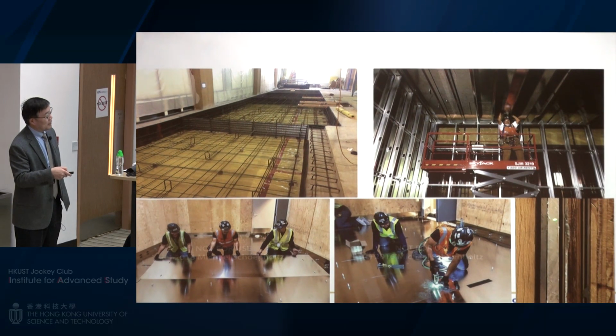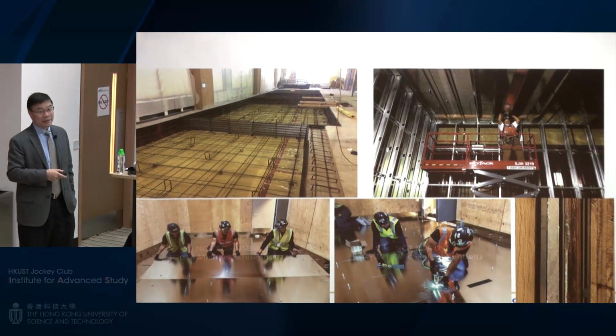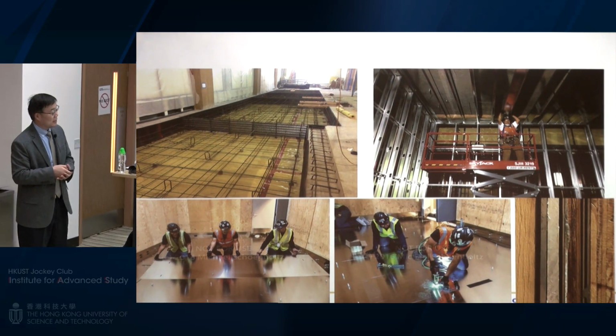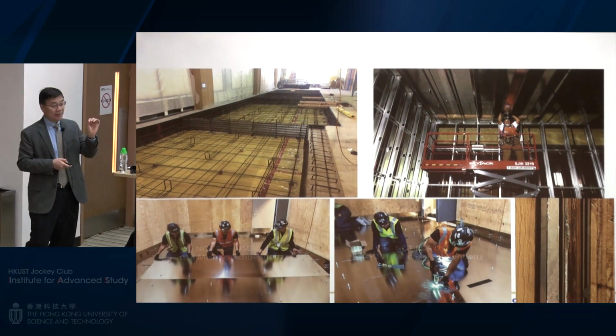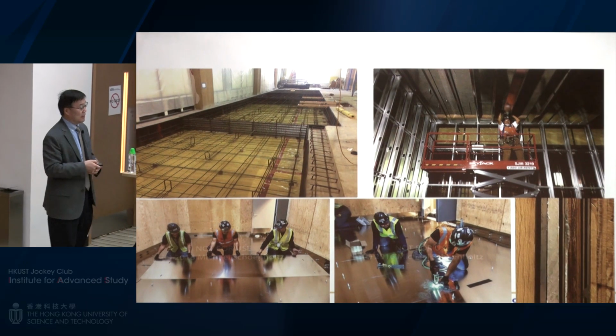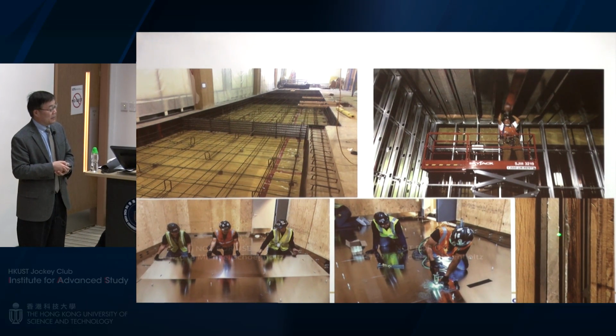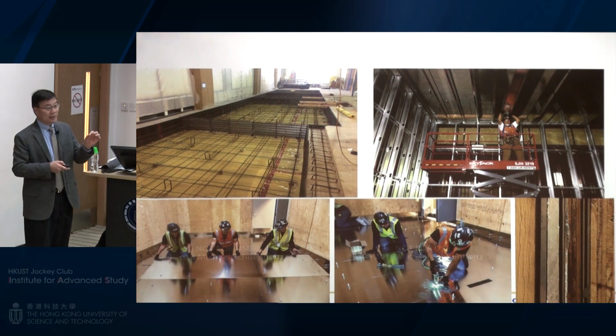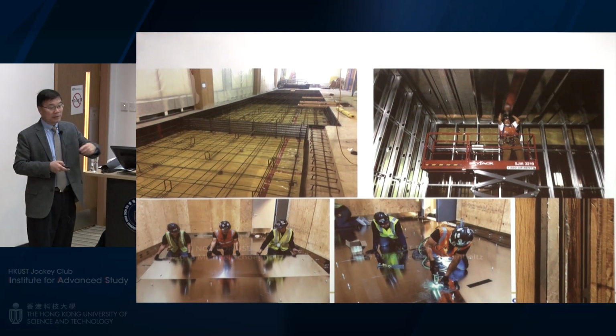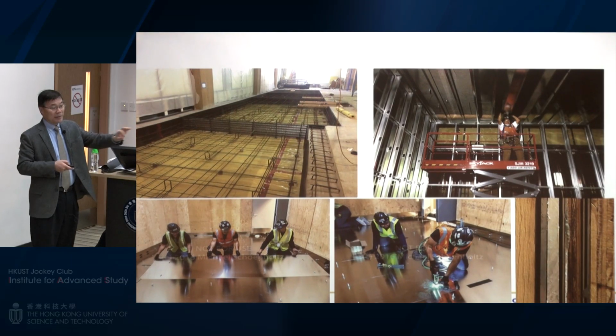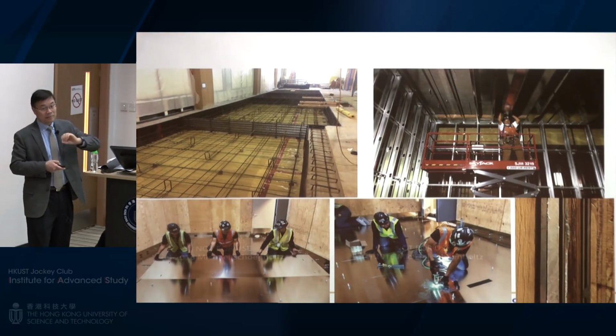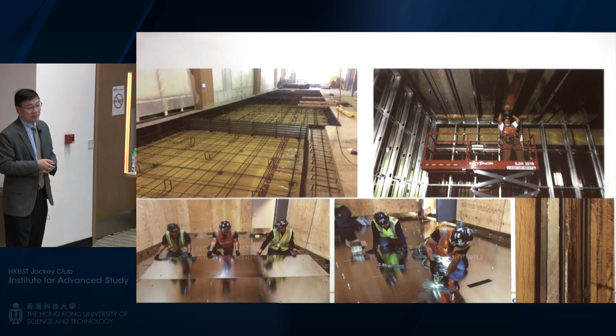So first we have a single layer of steel, soft iron. That is good for DC and AC, but not up to the standard for the dedicated STEM. And then we have one layer of quarter-inch aluminum, which is good for AC, the eddy effect, perfect for AC. And then we have to further shield the near DC. For example, when an elevator is moving, or even a big body, even a few people working together around the room, outside the room, you will see some small change.